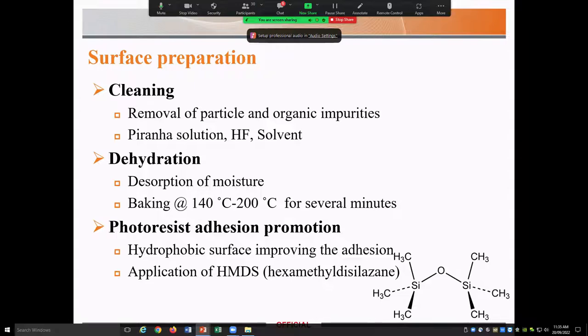So the very first aim in the lithography process is to generate a defect-free uniform film that has good adhesion to the surface. To do this, we may need to do some surface preparation. The first one is cleaning, which is just to remove the contaminants from the surface. Depending on the type of contamination, we may use different techniques, from piranha solution, HF acid, solvents, UV cleaning, or any other type of cleaning process.